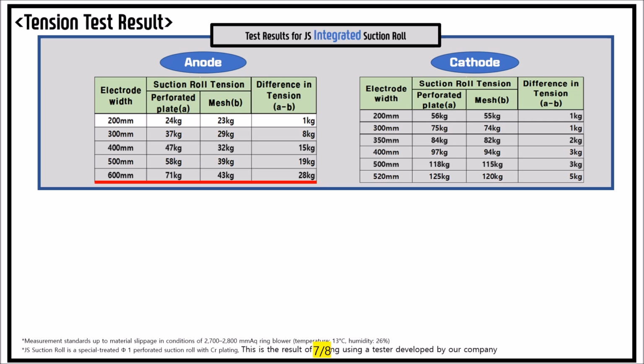This indicates that for the anode, as the electrode width increases, the tension value of the perforated plate type is significantly higher than that of the mesh type. For the cathode material, at an electrode width of 200 millimeters, the tension value of the perforated plate type was 1 kilogram higher than that of the mesh type. At 350 millimeters, the perforated plate showed a 2 kilogram higher tension. At 500 millimeters, its tension was 3 kilograms higher. This indicates that for the cathode, the perforated plate type achieves tension values equal to or exceeding those of the mesh type across various electrode widths.